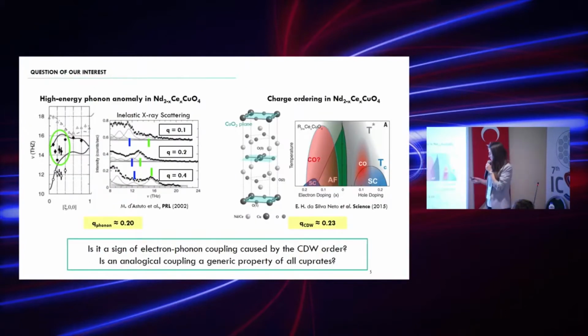That's why here I'm showing results from the inelastic X-ray scattering technique and the anomalous softening of a high-energy optic phonon mode for neodymium cerium copper oxide. It was reported nearly 20 years ago. Here it is marked by this green circle, and now I explain what it means. It means that this green high-energy phonon mode softens around Q equals 0.2, while the second mode, the blue one, stays at the same energy. And it was reported for Q equals 0.2.